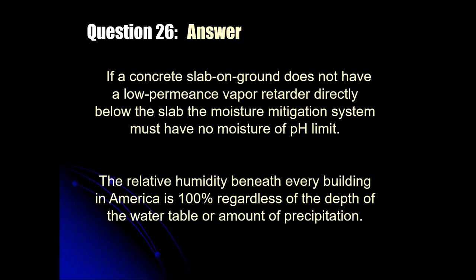Well, any slab that doesn't have an effective vapor retarder directly under the concrete, if you put sand or gravel over the top of it, it basically negates its effectiveness. And I know we did that, and we told people to do that a long time ago for many years, but everything has changed. All of the standards, all the recommendations today: the vapor retarder's got to be in direct contact with the underside of the slab. If it's not there, then the moisture mitigation system must have no moisture or pH limits.